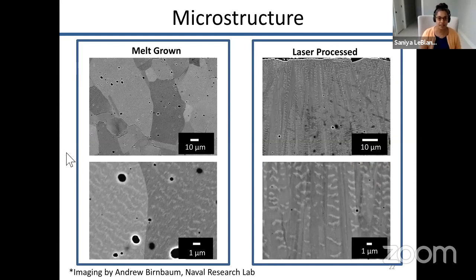So on the left-hand side, this is a thermoelectric material that is melt grown, made with one of the very traditional techniques for making thermoelectric material ingots. You can see with the melt grown material, you have these more equiaxed grains that are distributed. On the right-hand side, you see a micrograph of our laser processed material, when we have built up this material layer by layer using this laser additive manufacturing process.